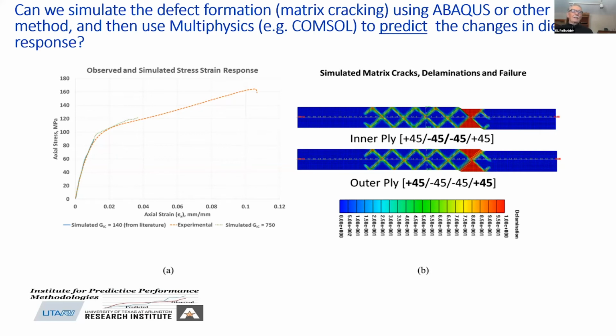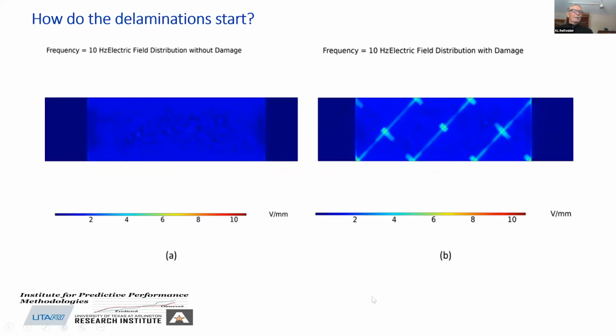And most of you have already guessed, that's delamination. We look locally where the cracks cross, the plus 45, minus 45. And by the way, we're working here at 10 hertz. So these are low frequency results. And of course, we do indeed see the delamination regions where the cracks do cross. First noticed by Highsmith, I think. And that's what we expected. They do indeed couple up with each other and combine through the thickness.